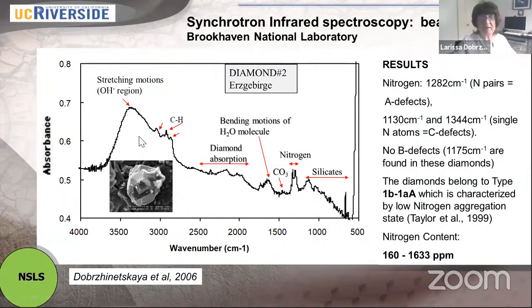We conducted more experiments with synchrotron infrared spectroscopy on different diamonds, and this is another sample, again a diamond from Erzgebirge. We see here the stretching OH region again, again CH radicals, and then we see molecular water, we see CO2, nitrogen, and silicates. What is the result? I summarize. We found nitrogen. And there is a concept that we can recognize nitrogen defects. This concept was developed by Wayne Taylor and published in 1999. And now we know that according to the nitrogen aggregation, a diamond can be separated and recognized as a diamond from kimberlitic terrain or a diamond from ultra-high pressure terrain.